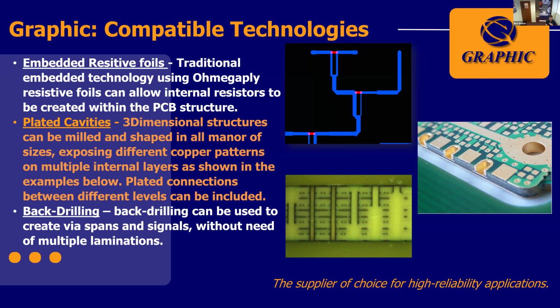What we always say is that we want to minimize your stubs. And here at Graphic, we can work to a max stub length of around 100 to 125 microns. What I wouldn't want to see on a design is back drilling potentially coming into your flexible section. Let's just say you have two flexible layers within the middle of your construction. It's a 6 layer. I wouldn't want to see designers say, we want you to back drill from the bottom side to break the connection up to the first flexible layer, and then to not cut the copper on the next layer.